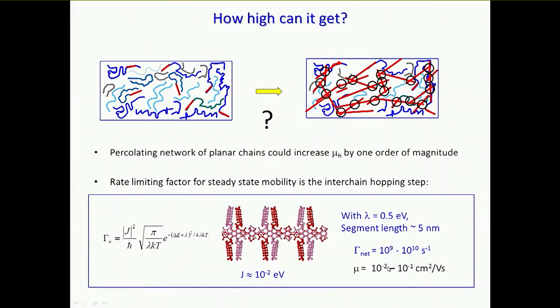And my estimate is around about 10 to the minus 1 centimeters squared per volt second for steady state transport. But in other conditions, it may appear to be higher. And that would really argue that if we wanted to increase mobility, improving the transport along the chain is not on its own going to get us there. We need to do something about finding the conditions to improve the coupling between neighboring chains to maximize this rate limiting step.